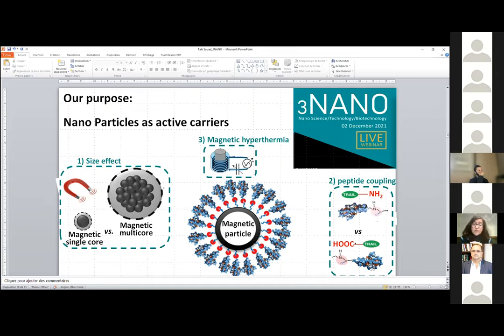So in this context, we decided to prepare magnetic nanoparticles, namely iron oxide nanoparticles of different sizes, single core and multi-core, because we know that the magnetic properties are very dependent on the microstructure of the particles. We also decided to attach TRAIL covalently to the particles because covalent bonding is the most robust one, particularly in biological media. And also we wanted to apply an alternating magnetic field and to check if there is any synergetic effect between magnetic heating induced by an alternating magnetic field and the apoptotic properties of TRAIL.